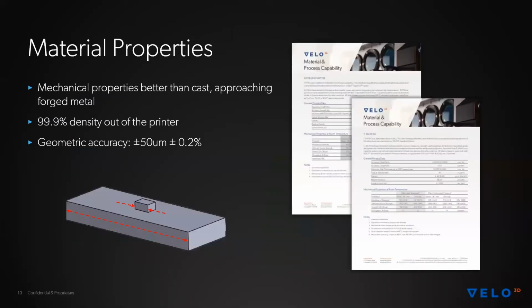Our material properties are better than cast, we like to say. In some cases, we approach the properties of forged or wrought materials. The density is 99.9% right out of the printer. Our geometric accuracy of small features is plus or minus 50 microns. And on larger dimensions, we expect to hit between plus or minus 0.2% of that nominal dimension. All of our material properties can be found on our website.